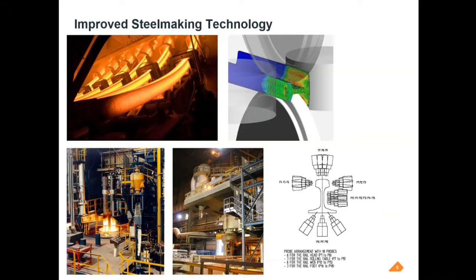And that's not just at the ends, that's for the full 120 meter rail we produce all the way down its length. It's got to be within that tolerance band. And it's important for the ride comfort, the running surface, the height of the rail. You don't want a lumpy, bumpy rail if you're going to be flying across it at very high speeds. In the bottom left corner, you see we've got a ladle arc furnace and some secondary steelmaking activities going on. That's now mandatory in modern steelmaking specifications. But what that allows you to do is control the temperature arriving at the caster very well. You can refine the chemistry to very tight control levels. You can bubble argon through it and make it homogeneous. You can get better quality steel.